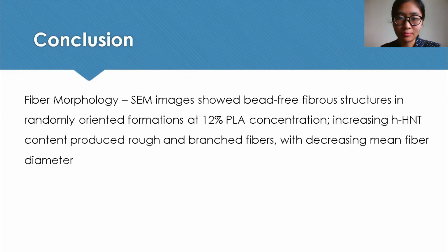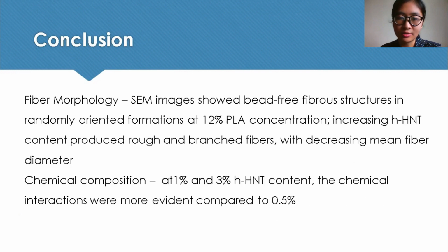The fiber morphology of the pure and composite fiber mats was good. Some images showed bead-free fiber structures in randomly oriented formations, which was also desired in many published papers. FTIR results also revealed successful interfacial interaction between the hydroxylated clay and the polymer matrix. At 1% and 3% HHNT content, the chemical interactions were more evident compared to 0.5%.